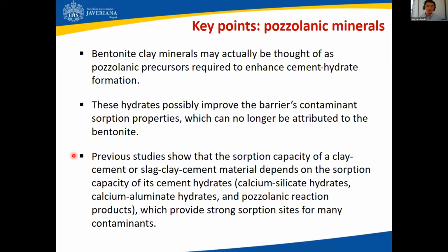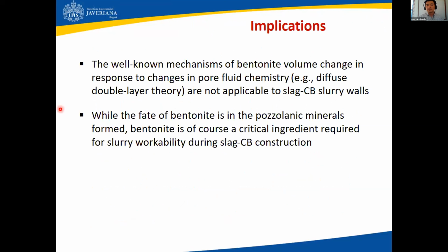So what we do know, though, is that the field of lime or cement stabilization of swelling soils has told us that the sorption capacity of a clay-cement or slag-clay-cement material depends on the sorption capacity of the cement hydrates. And those are the hydrates I'm talking about when I mention pozzolanic products. These materials or minerals provide strong sorption sites for many contaminants. And this is a widely unexplored field of research that we are looking forward to tackle in the next few years.